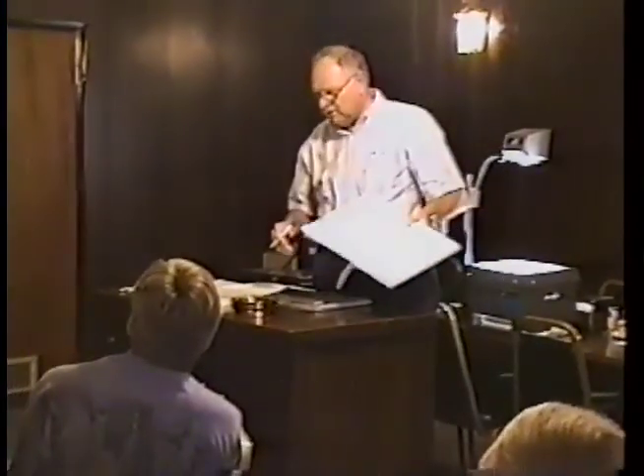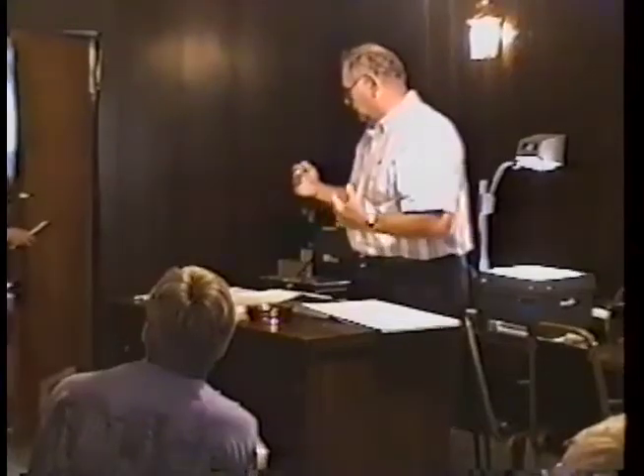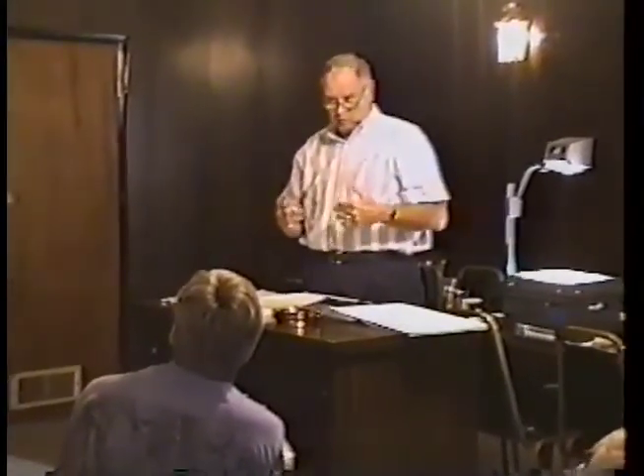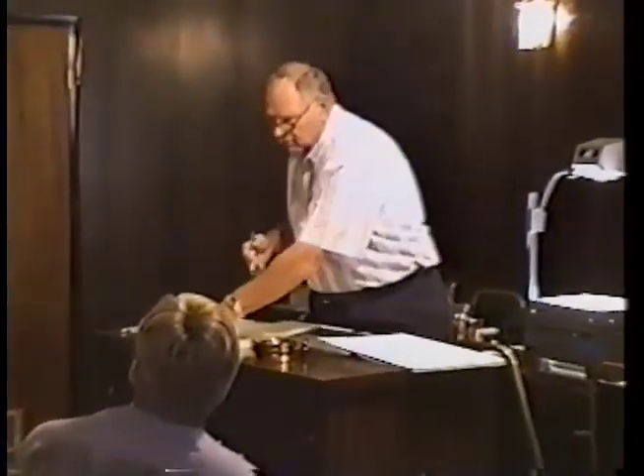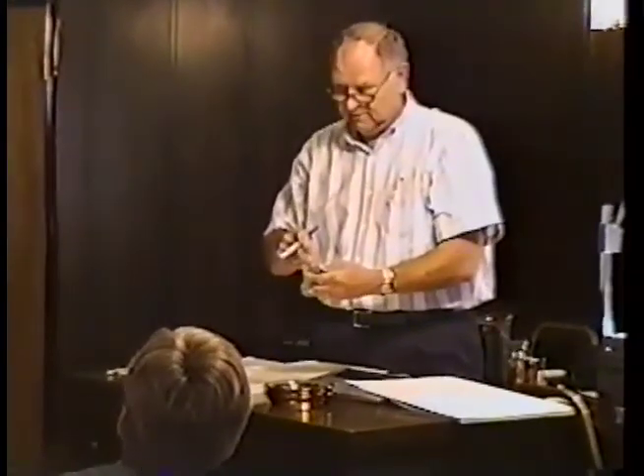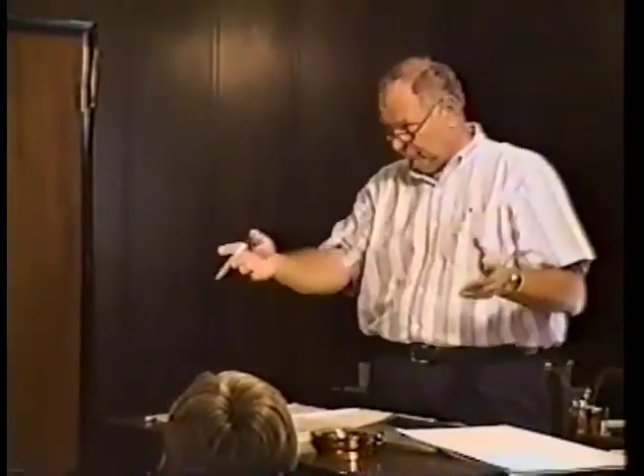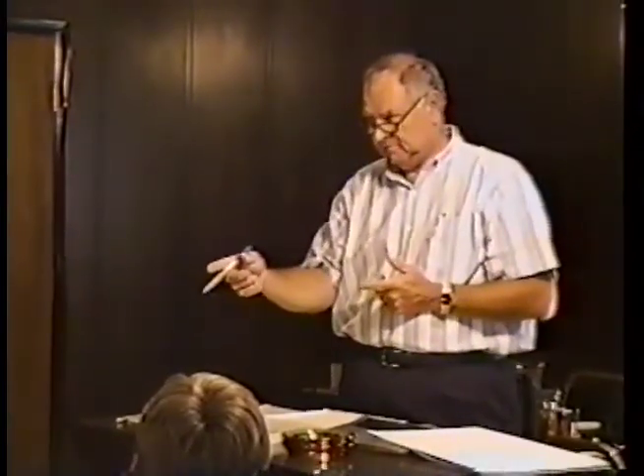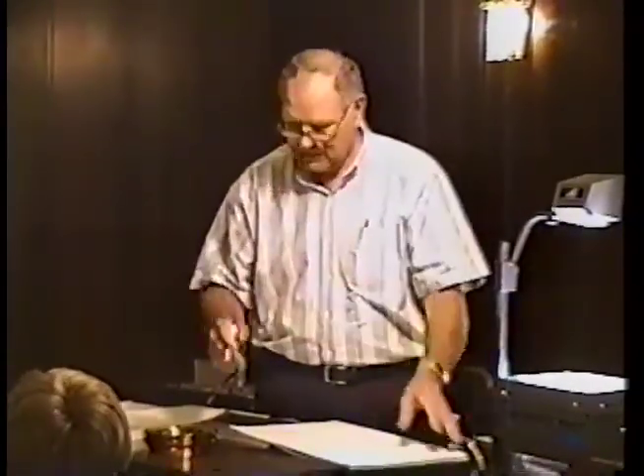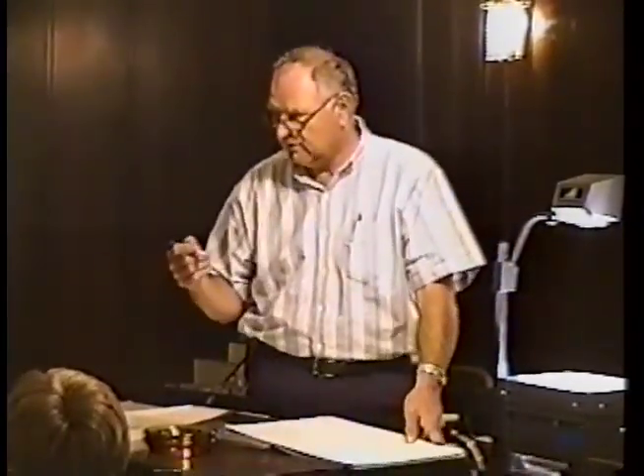The chrome, as I mentioned before, the care that's taken in the preparation of the surface is reflected in the chrome because chrome does not flow. When it's plating on, it doesn't flow like paint on a wall or anything like that. It plates in those little nodules like this, and it builds on itself until it reaches a point, and then it builds on more after that. But it doesn't flow and fill holes, casting pits, sand holes, those kinds of things. It's not like nickel, not like a softer metal that will fill and cover it over.